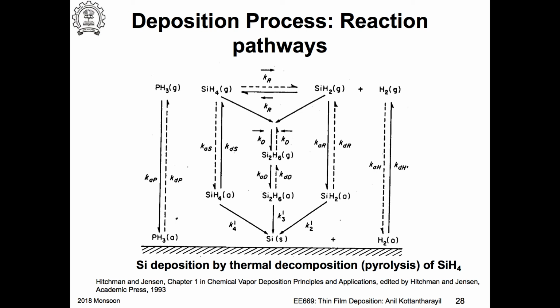Okay? And something that we usually don't discuss when you describe the CVD reaction is that you have a main gas flow and all these gases are coming in. Okay? A very small fraction, about 10 to 15%, is actually used in the deposition. The rest just flows out. Okay? And you can imagine that in VLSI applications, we are talking about very high purity, six to seven nines purity silicon and phosphine. So very expensive gases, they just go out. Okay? So that has to be treated before you let it out into the atmosphere.